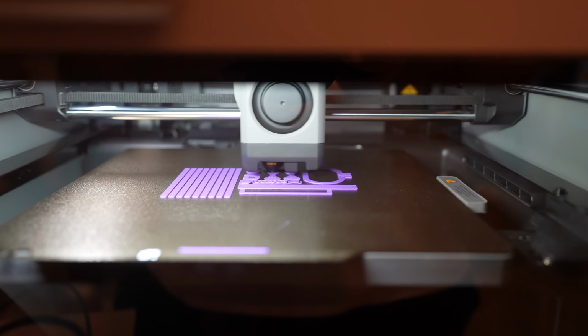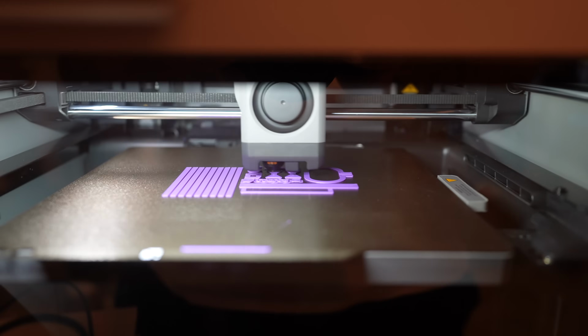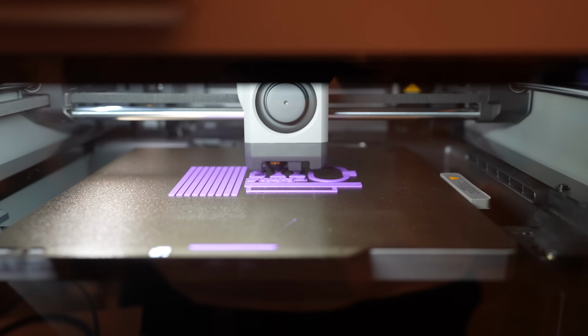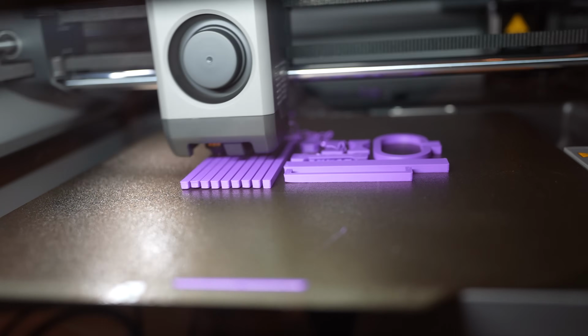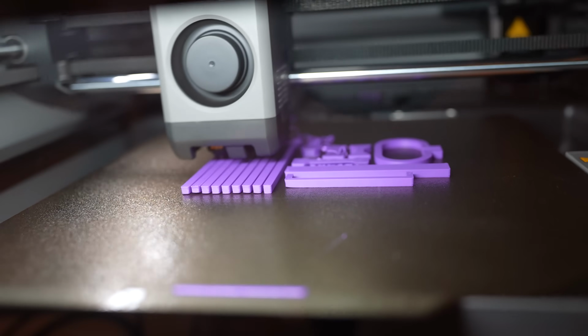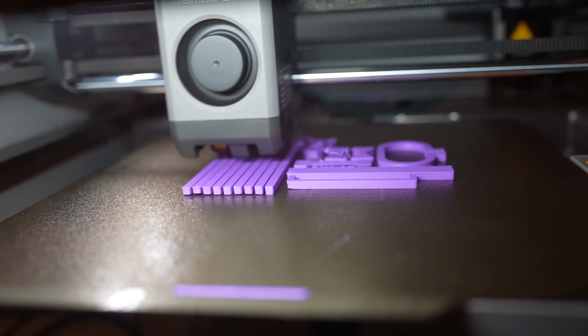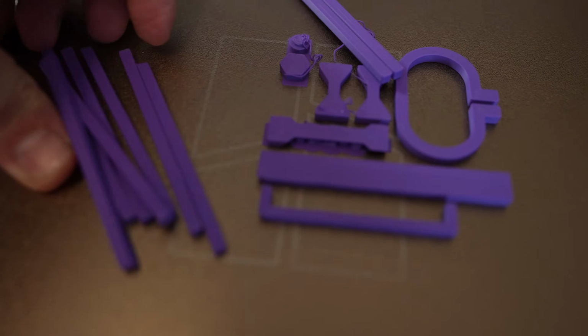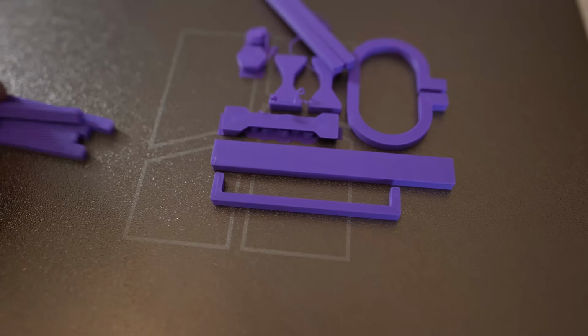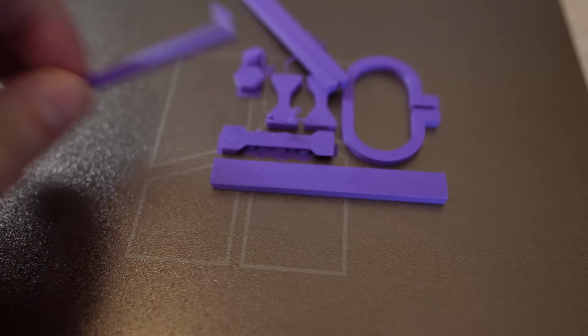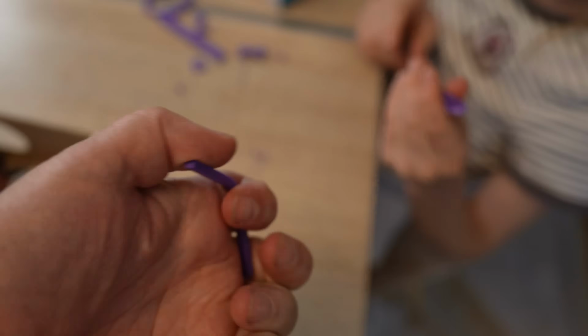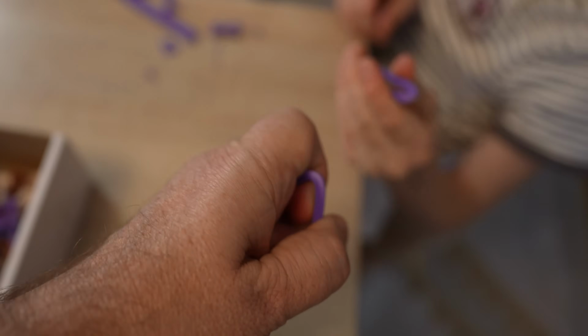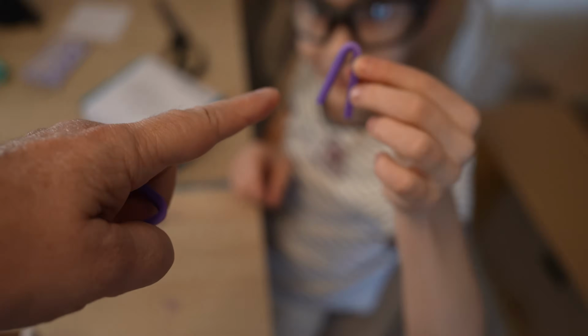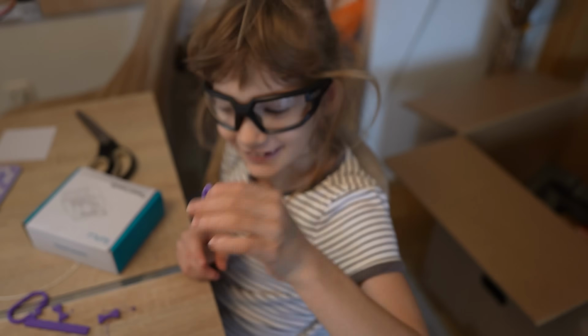This is now the 4th layer, but now instead of 2, this will be 2.5 hours of printing. Another print I have to stop, warping, more and more similarity with ABS. Adhesion is good, acceptable actually, but because of that warping it reduces. Before the next print, an interesting property: we could completely bend it. Actually she wanted to break it and she noticed this.